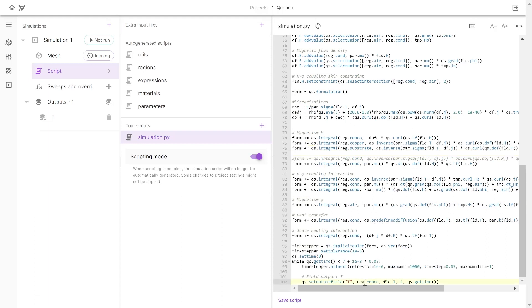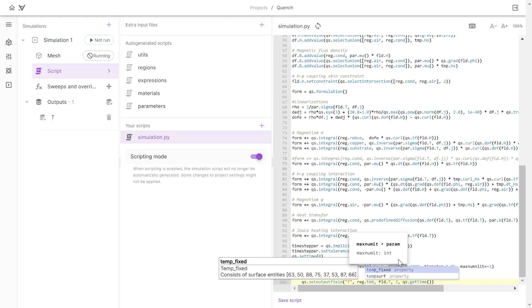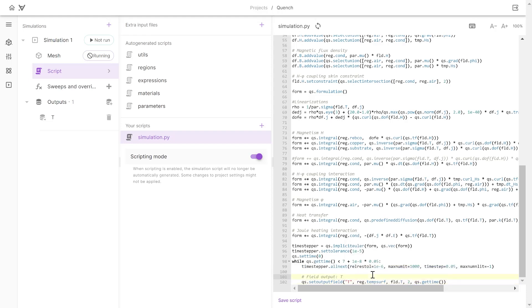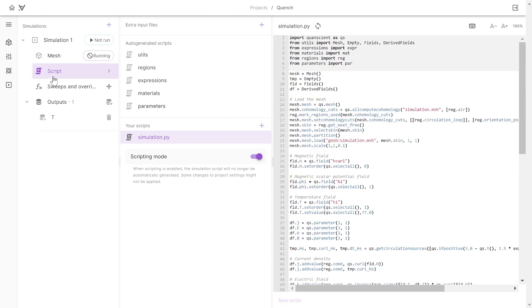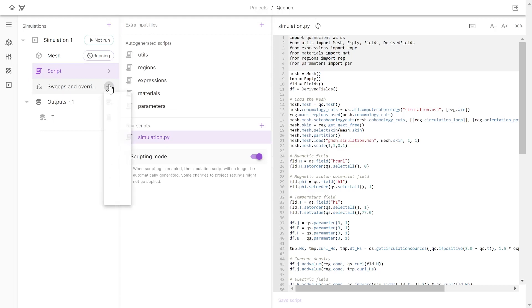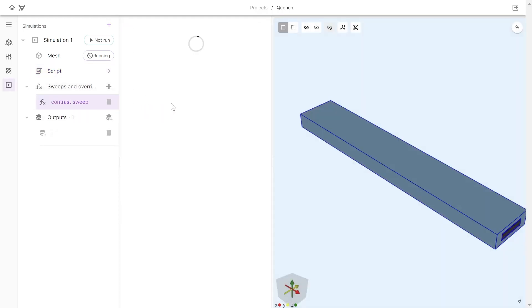As a last step in the script, I set the temperature field on the surface of the REBCO layer rather than the whole volume — this reduces data amount significantly. We save the script. The setup is now configured for a contrast of 60%, meaning 60% of the critical current density in the middle of the tape, and I want to sweep over that. In the sweeps and overwrite section I select the contrast expression and define a linearly spaced vector from 60 to 100% in five steps.